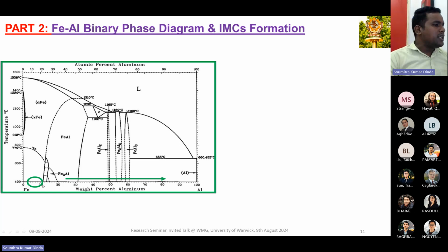Now we can see that nearly 10 to 11% aluminum is soluble in the iron matrix. So if our aluminum addition in steel is less than 10 to 11%, that will give you a solid solution, giving better mechanical properties. But if we add more, then what will happen? Then there will be chances for different types of compound formation.